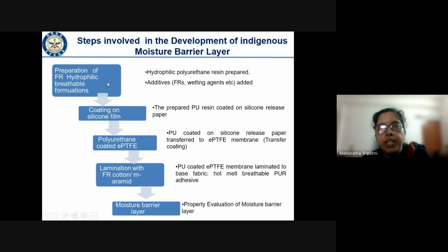These are the steps involved in the development of the indigenous moisture barrier layer. In this, hydrophilic polyurethane resin is prepared, and FR additives and wetting agent were added to this. And then this prepared PU resin was coated on silicone release paper, and then the PU coated on silicone release paper was transferred to EPTFE membrane by transfer coating, and then the PU coated EPTFE membrane was laminated to base fabric with the help of hot melt breathable PU FR adhesive.